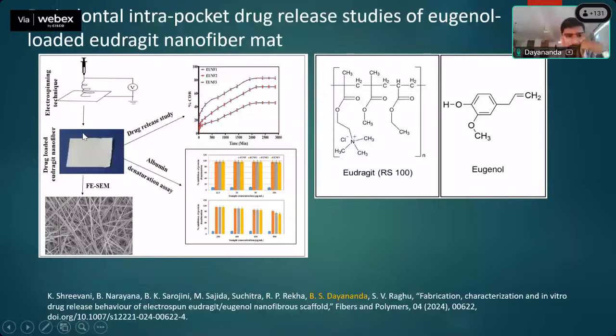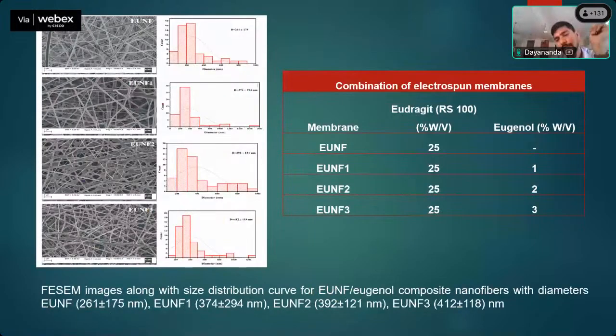Release studies here also were loaded, and 4 different nanofiber mats were prepared by loading different concentrations of eugenol. The nanofiber morphology is different for different nanofiber mats, so the diameter of the nanofiber will change from one mat to another depending on the drug loaded.